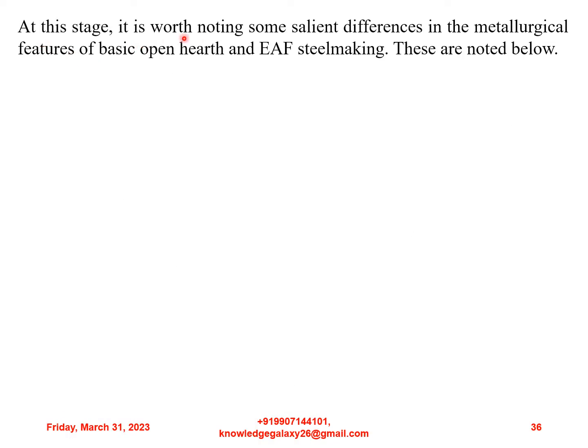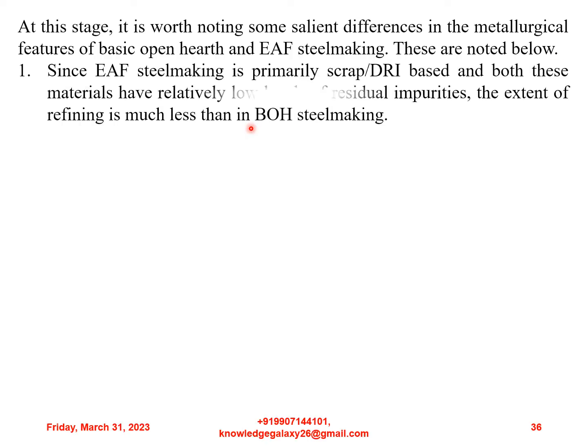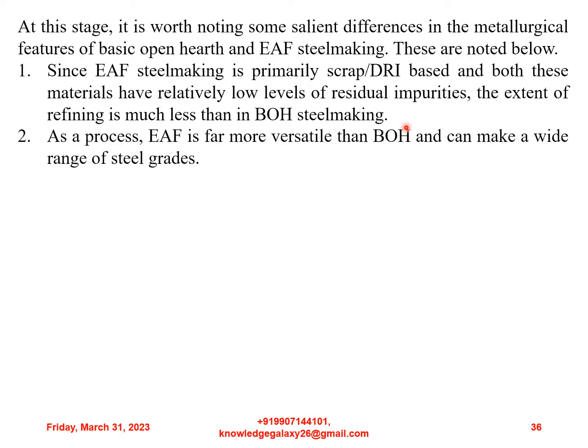At this stage, it is worth noting some salient differences in the metallurgical features of basic open hearth and electric arc furnace steelmaking. These are noted below. First, since electric arc furnace steelmaking is primarily scrap or DRI based and both these materials have relatively low levels of residual impurities, the extent of refining is much less than in basic open hearth steelmaking. As a process, electric arc furnace is far more versatile than basic open hearth and can make a wide range of steel grades.